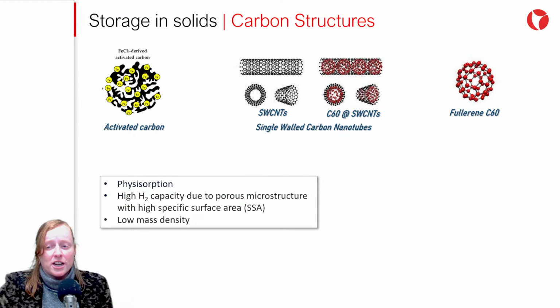Fullerenes. These spherical structures have been investigated as potential candidates for hydrogen storage due to their hollow interior and high surface area, which could provide sites for hydrogen adsorption. However, they have not proven to be a practical solution so far, as they exhibit less specific surface area than other alternatives. Hydrogen molecules diffuse into the C60 network without dissociating, resulting in around 0.2% by weight of H2.